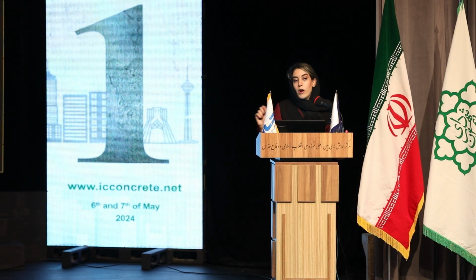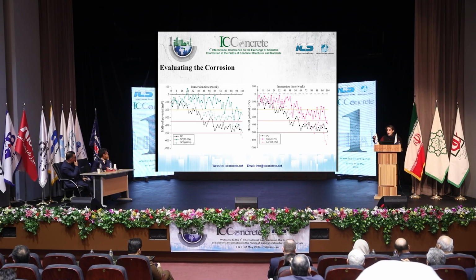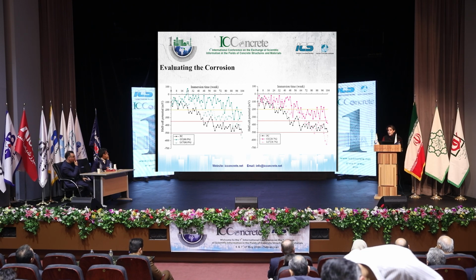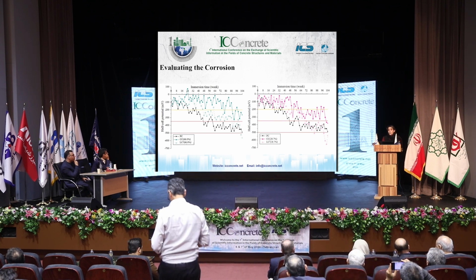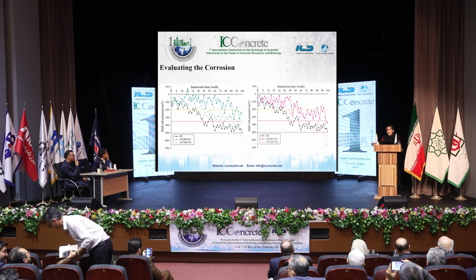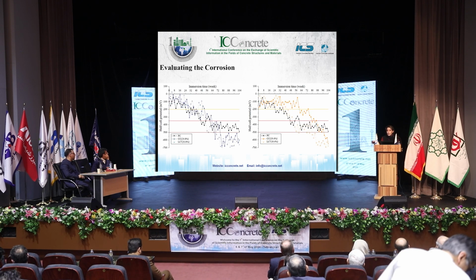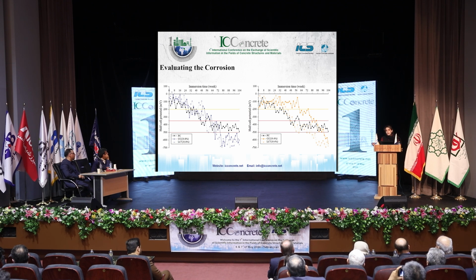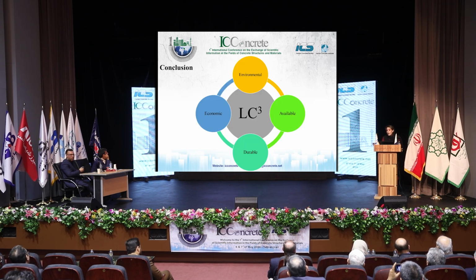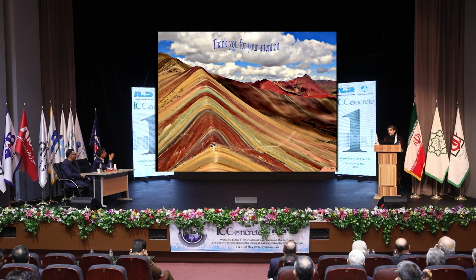The time of chloride-induced corrosion initiation was shorter in LC3 and calcined clay because of better permeability and also increased chloride binding capacity. But after the initiation, after 350, the rate of corrosion increased in the samples because of lower alkalinity. And finally, I can introduce LC3 as an environmental, economical, available, and durable approach for our future. Thank you.